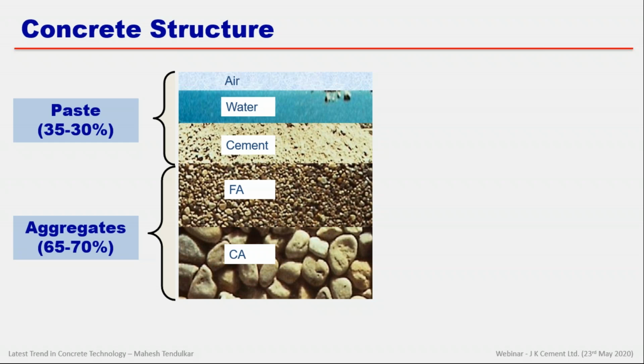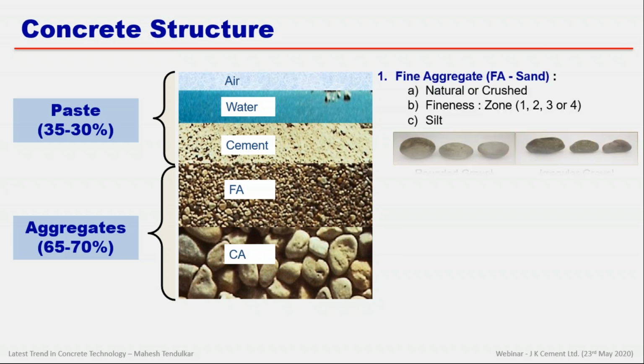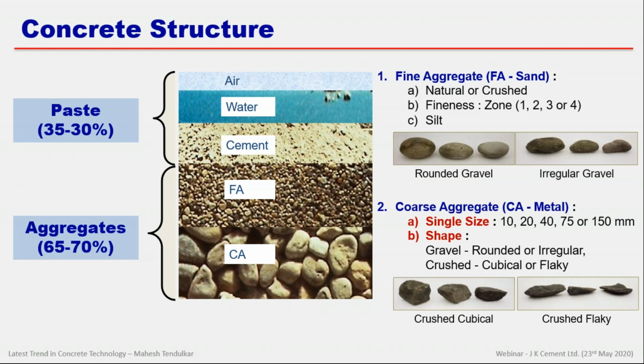but when we go to higher grades, aggregate becomes more critical and the paste will be very strong. Concrete will not fail in bond, but the aggregate will fail. So whenever we go for M50 and above concrete, we should be very cautious about various types of coarse aggregate and fine aggregate. And nowadays, we have no option but to use coarse aggregate, 10 mm, 20 mm single size aggregate, VSI. I will touch that point in detail later.